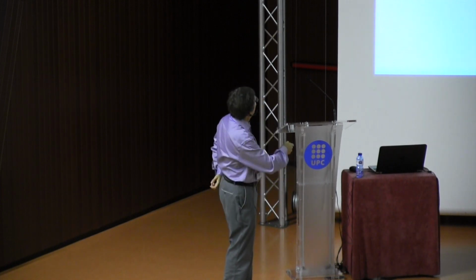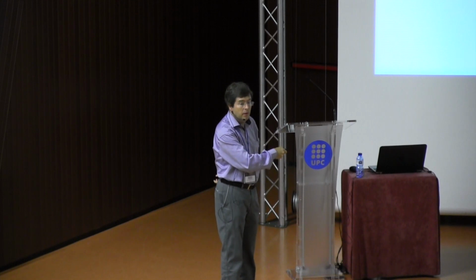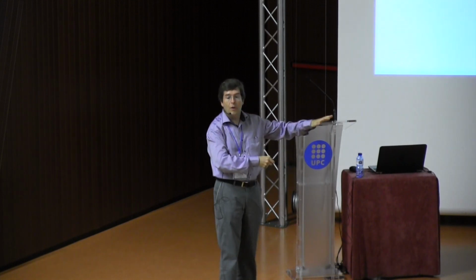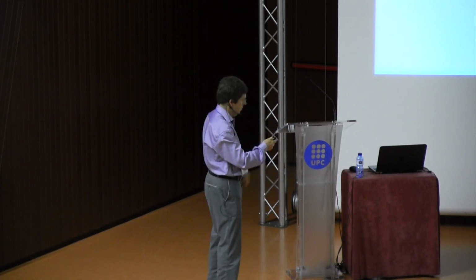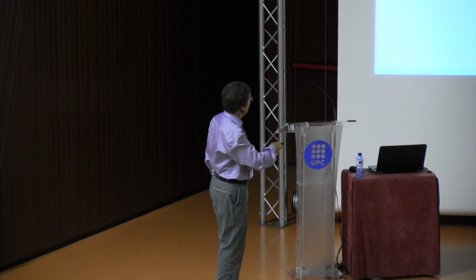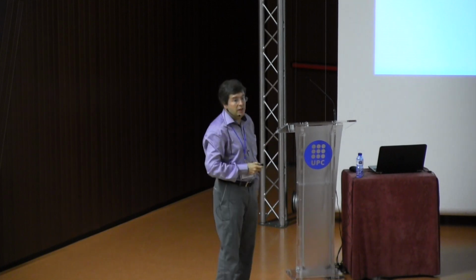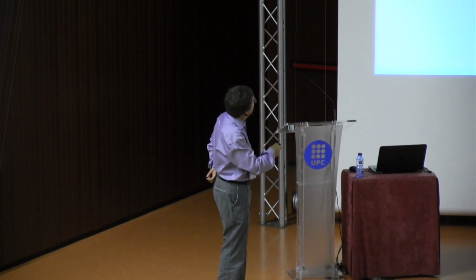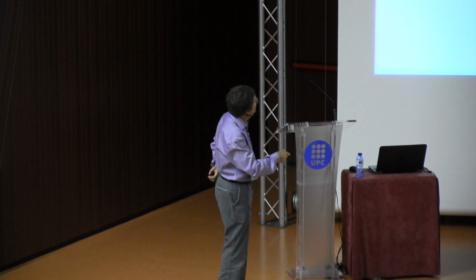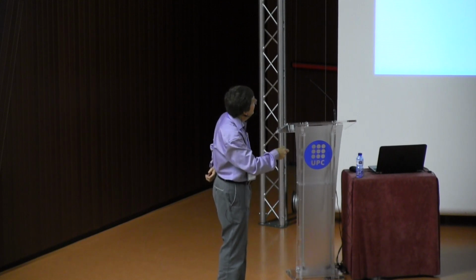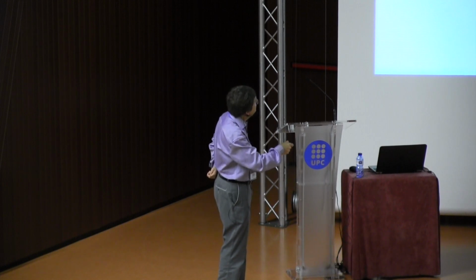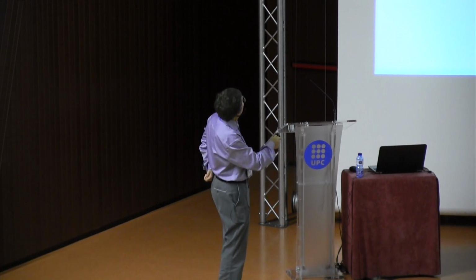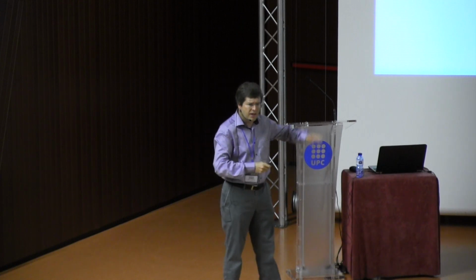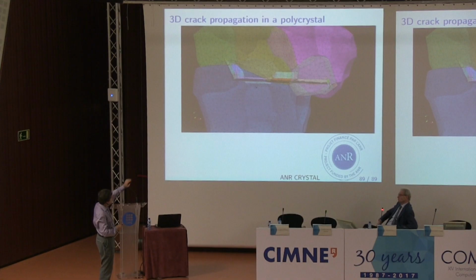And why there is such a complicated pattern, this is an experiment here, a measurement by X-ray tomography made in Grenoble, at the synchrotron facility. And what we have done is simulate this in crystal plasticity, where you see that the reason for these abrupt changes in the crack path is that there are grains in front of the crack, and the crack propagation is different depending on the orientation of the grains, this one or this one. The most critical one is this one, and you see here there is a crack propagation. It comes at the grain boundary, and then it crosses. There is hesitation again, a few cycles, and then you have a propagation.